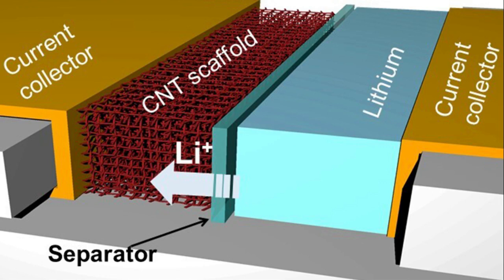These batteries also have a more insidious problem. Sometimes lithium ions do not evenly deposit on the anode. Instead, they accumulate on the anode surface in chunks, forming tree-like structures called dendrites. Over time, the dendrites grow and eventually pierce through the material that separates the battery's two compartments. This breach causes the battery to short-circuit and can set the device ablaze. Growing dendrites also affect the battery's performance by consuming lithium ions, rendering them unavailable for generating a current.